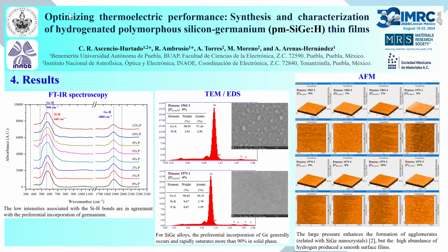It disappears. The absorption peak at 1,880 cm⁻¹ corresponds to the germanium-hydrogen bond in stretching mode. We can see how it clearly reduces as the phosphorus content increases. For all of the aforementioned, we can say that the phosphorus incorporation reduces the concentration of weak silicon-silicon bonds and enhances the presence of germanium-hydrogen and silicon-hydrogen bonds.